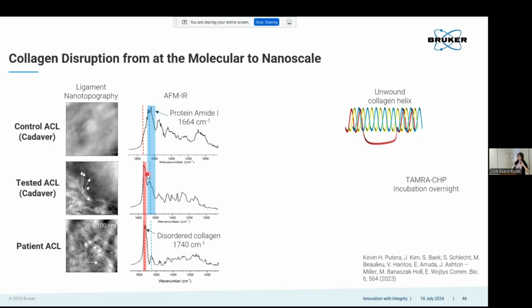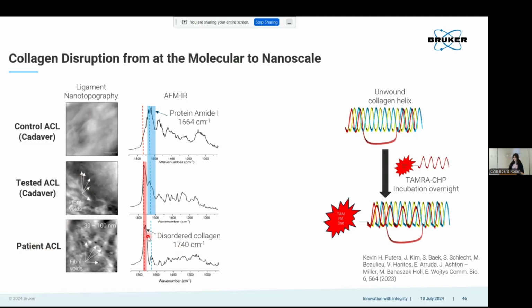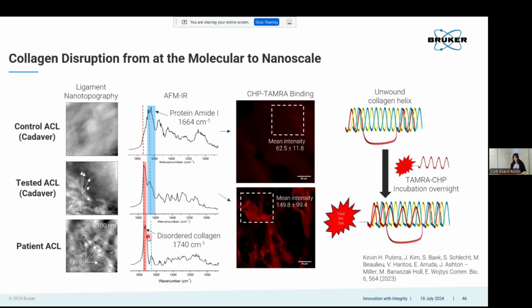So you have a change in the chemical structure due to this wear cycle and an unraveling of the collagen fibers. If you look at a patient ACL from somebody whose ACL has failed, you see a similar result where you see this highly disordered collagen. We can also look at this using fluorescent markers, where you attach a fluorescent marker that targets specifically the unwound collagen, and you see a similar result, right? We see areas where you don't have any variation in the control example, and in the tested example you start to see areas where the protein has unraveled, right? This is the mechanical wear that you're putting onto your ACL.